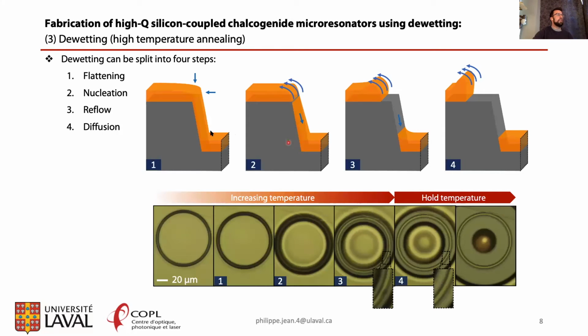We can understand the dewetting process of the microtrench in 4 steps. First is flattening of the glass, and at some point the glass will meet the substrate and create a hole, which we call nucleation. Then this hole will grow through a self-diffusion of the rim that retracts, and more interesting for us, the glass will reflow into the microtrench, leaving a very nice and smooth waveguide. This is what you can see here in the first few images. We increase the temperature, and at some point, in this case at 240 degrees Celsius, we hold the temperature, and the glass continues to reflow. We hold that for 2 minutes.